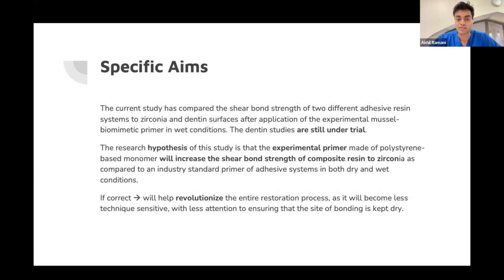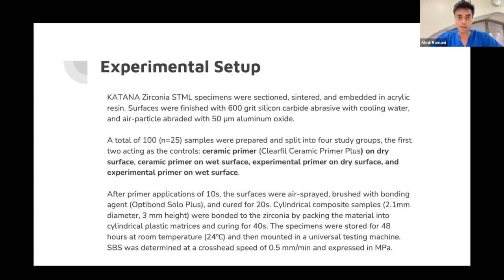And the research hypothesis was that the experimental primer would increase the shear bond strength of the composite resin to zirconia as compared to the industry standard in both dry and wet conditions. And if correct, this would obviously help revolutionize the entire restorative process because now we don't necessarily have to keep so much focus on making sure that the environment is dry. We can undergo the entire procedure without a rubber dam and without any attention to excess saliva.